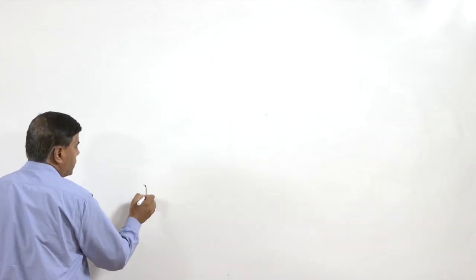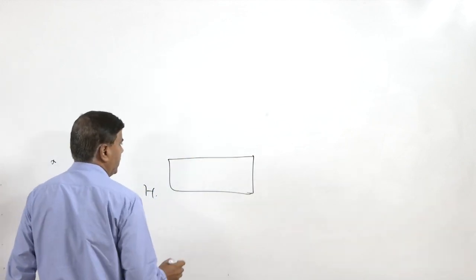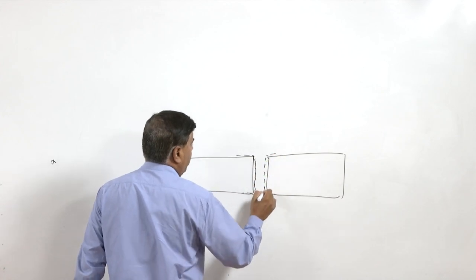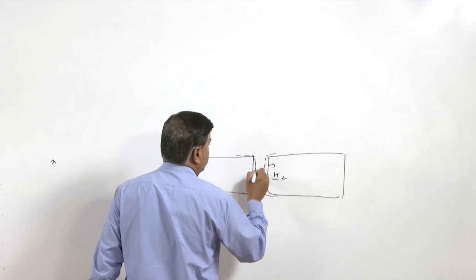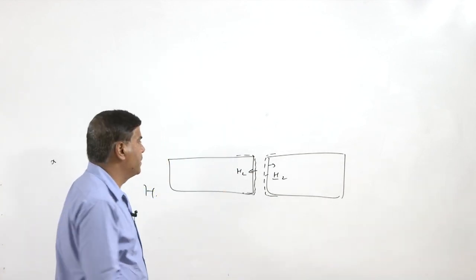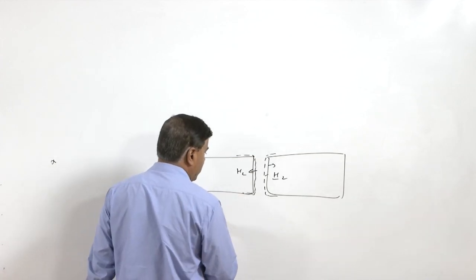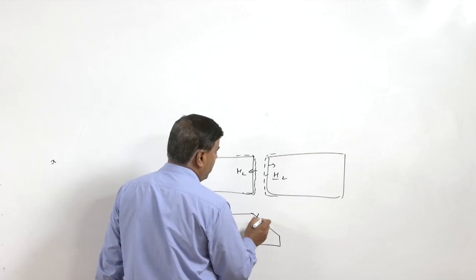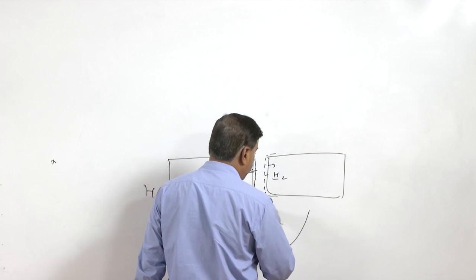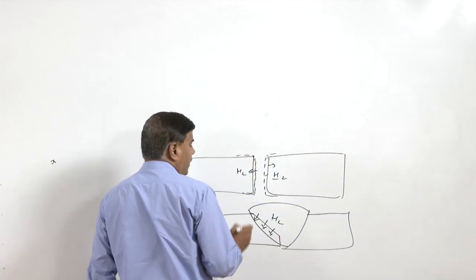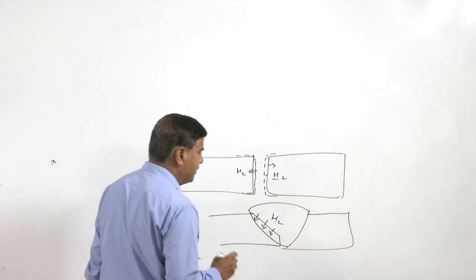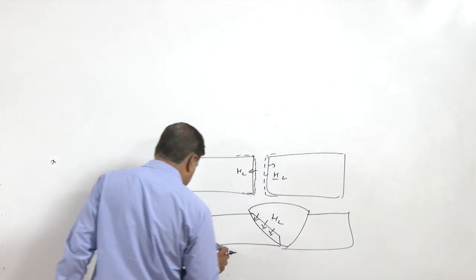When these hydrogen based acids are applied on the surface of the metal to remove impurities, frequently hydrogen gets introduced on the surface of the component, or in the subsurface region of the base metal. This introduction of hydrogen into the base metal has to be taken care of. If it is not, then the edges of the plates, prepared and introduced with hydrogen during cleaning, will subsequently lead, during welding or the development of a coating, to hydrogen related problems, which may be in the form of fine pores, or hydrogen induced cracks in the case of hardenable steels, or fine pores in the case of aluminium alloys.